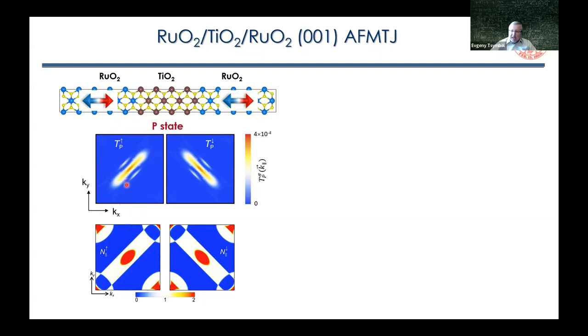So for each k-parallel, we compute transmission for spin up and spin down electrons. And this is the distribution in transmission we can find from this computation. As you can see on the bottom, I'm showing conduction channels as I've shown before. So you see there's some relevance between these two plots. The difference is mostly coming from the edges of the Brillouin zone, where transmission is substantially reduced because of suppression of the transmission away from the center of the Brillouin zone.